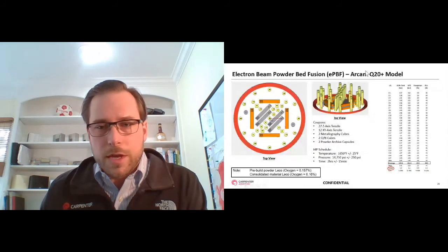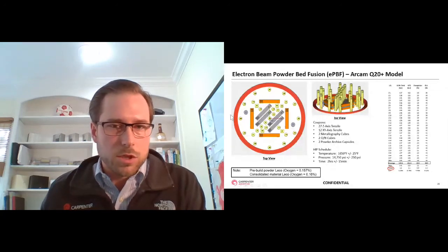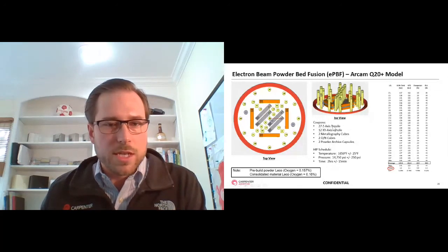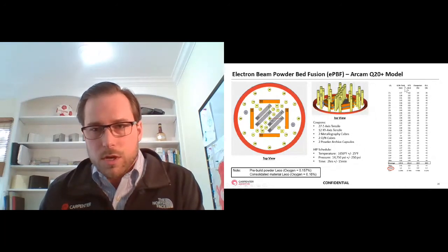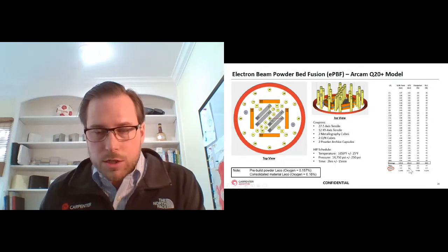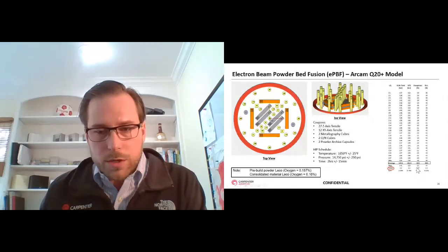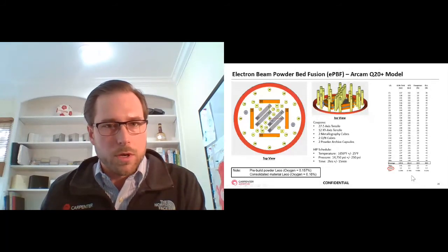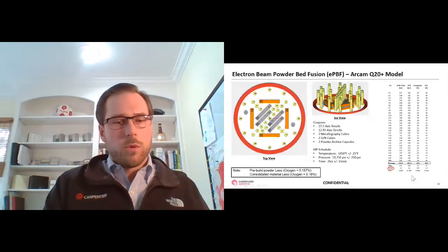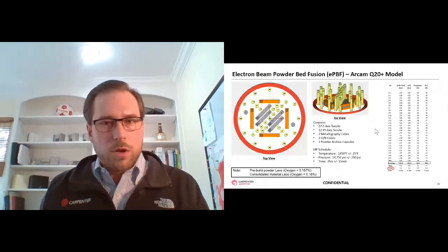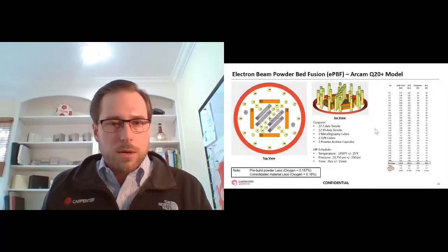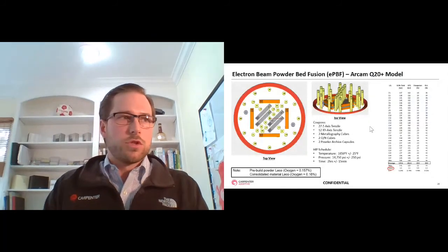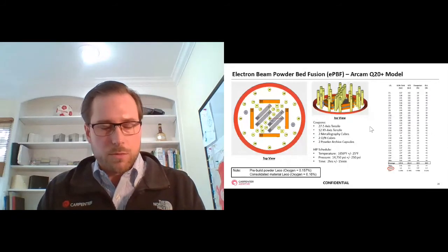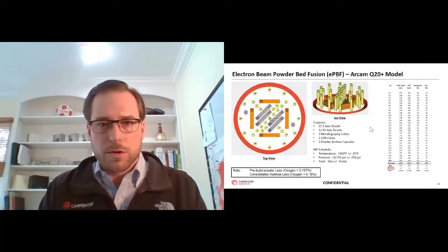And then for a Q20, okay, so this shows the build layout. There's 27 Z-axis tensiles, 12 XY-axis tensiles, and here are all the results. And again, showing our ultimate tensile strength with a standard deviation of 1.1 and an elongation of 0.9. So what we're showing in that is that we're translating these developments in materials through to repeatability in material characteristics and material properties.